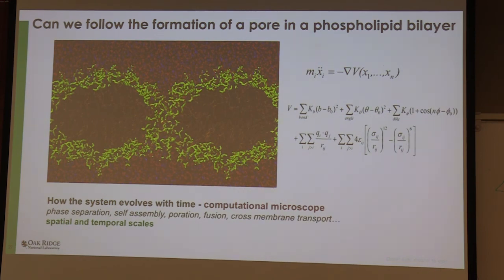And we can confirm this, because what we can do with experiments is deuterate, substituting the protons on these molecules that are forming the pore, and then scatter neutrons off of it. Neutrons, when they hit a deuterium, don't even see it, right? So you get this contrast. So you can actually confirm this with neutron scattering. So that's cool. Then you think, well, darn, I can do a lot more now, because I can confirm this poration phenomenon experimentally. So this little teeny itty bitty simple potential is good enough to do that.